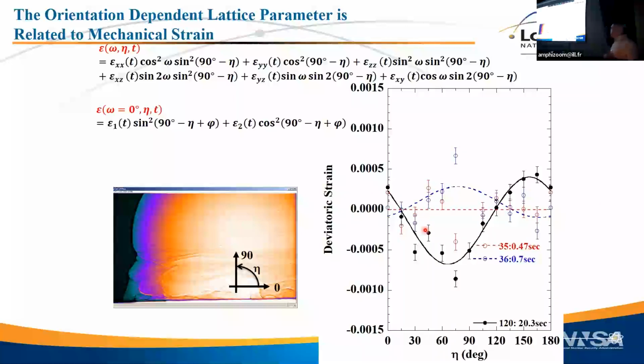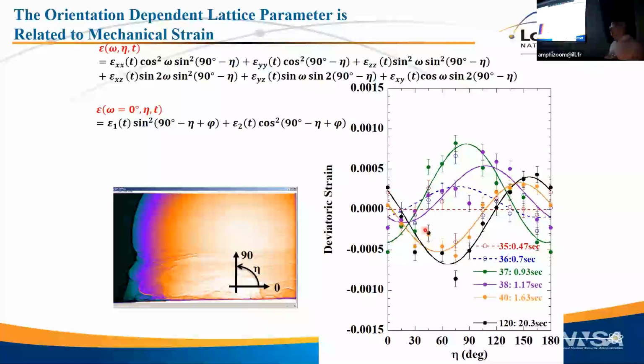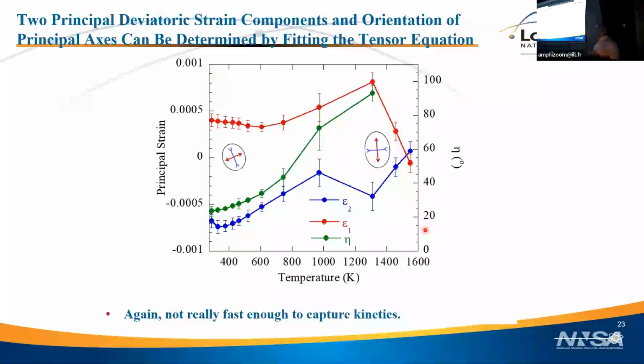As you progress on in time, you'll see that sinusoidal curve develop, and you see it both change in magnitude, and you'll also see it change in position. That's the shear strain evolving with time. Okay, so we can watch the evolution of that, and we can plot it. And again, we're really not getting enough time resolution. You know, here we are at maximum temperature where everything's zero. We get maybe one data point where the stress is growing, and then we're pretty much, not quite, but almost constant the rest of the way out.